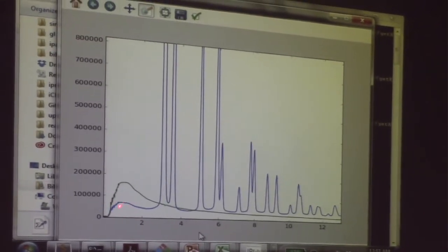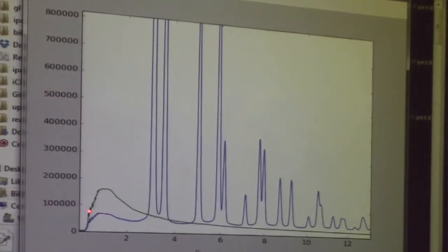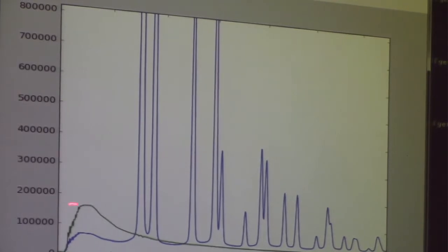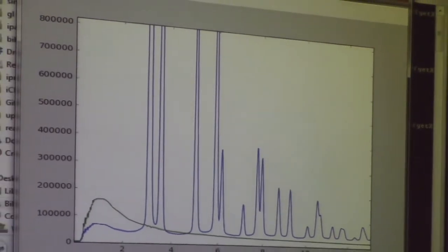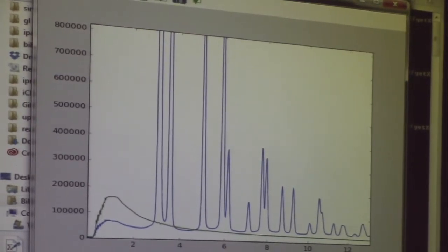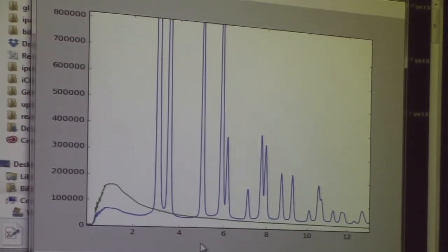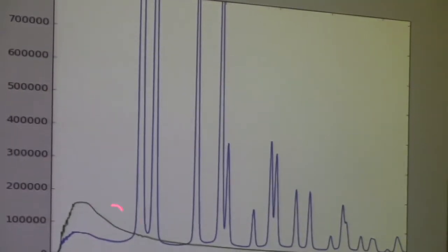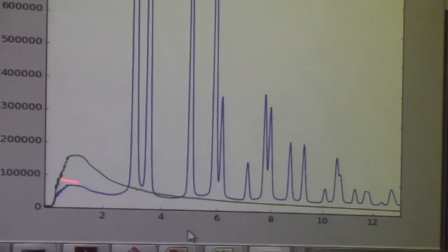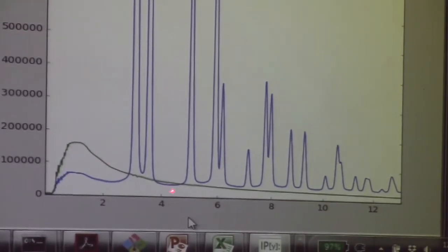And we can estimate it. We can look at this peak here, and let's say this is 10. So that's about 7. And this is about 16. So it's about 0.4, or 0.45. So we're expecting that we'll have to scale the background by a factor of 0.45. And this will bring this peak down to here. It's incorrect for this green line to ever be above the blue line.